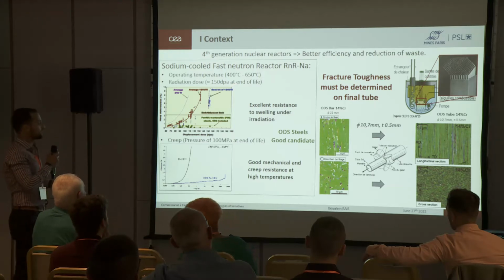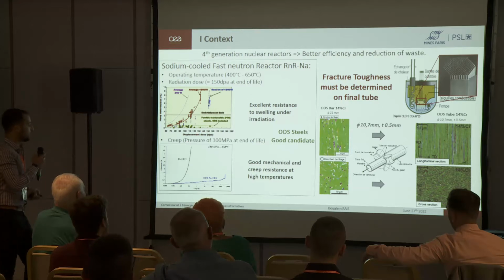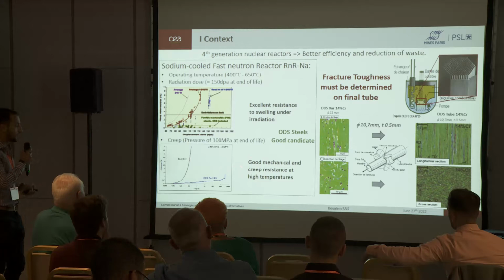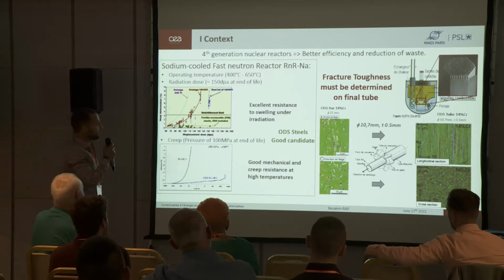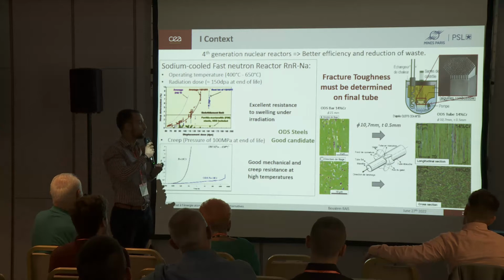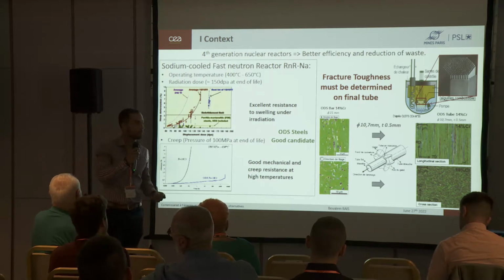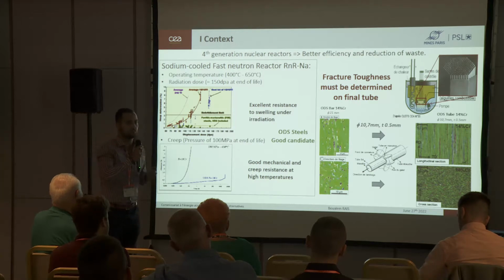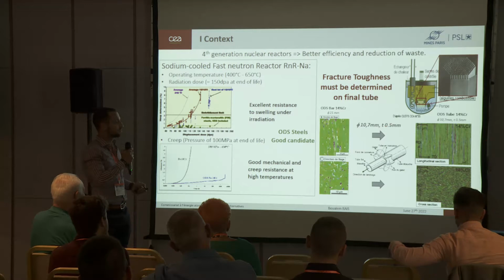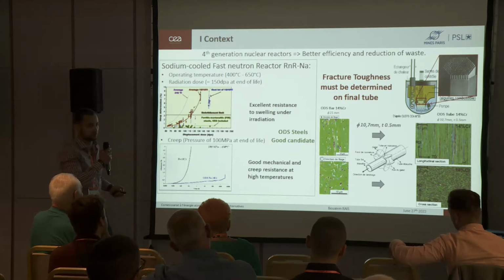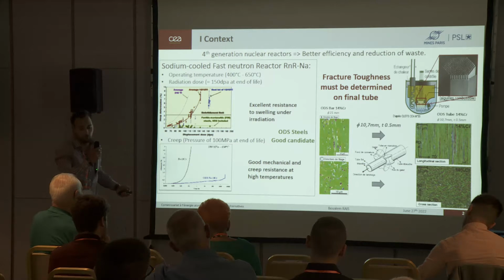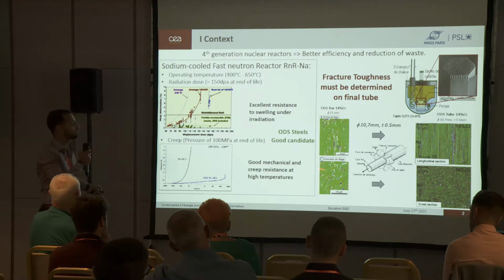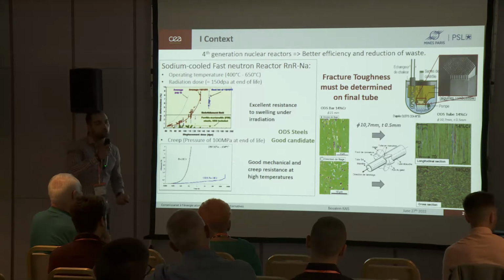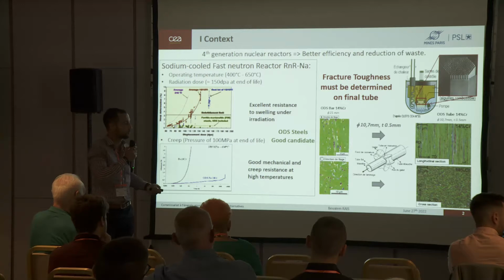It's thanks to their excellent resistance to swelling under radiation and their good mechanical and creep resistance at high temperature. But generally, an increase of mechanical resistance means a decrease of ductility. So it is important to assess the toughness of these materials during their development. The fuel claddings in French reactors are tubes with a 10.7 millimeter outer diameter and half a millimeter thickness, and the final geometry is obtained by cold rolling. This final step of shaping induces some microstructural modifications, so it modifies the mechanical properties of this material.